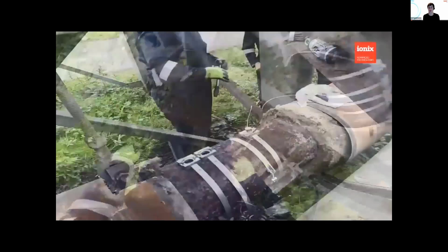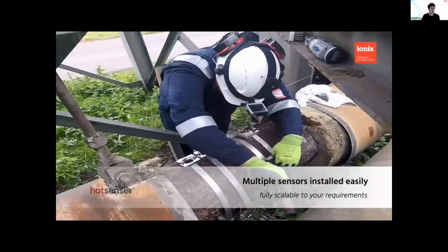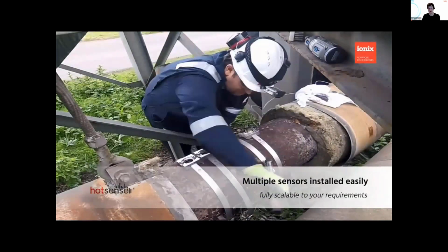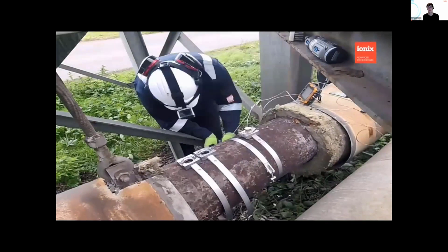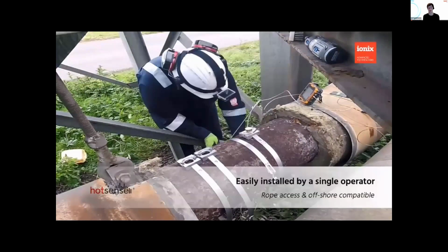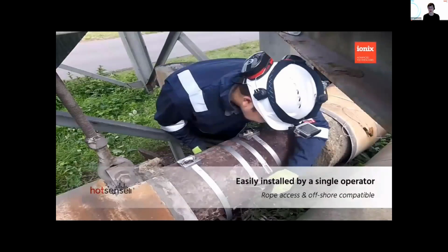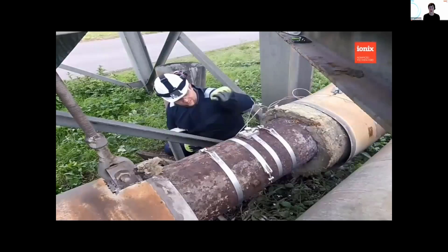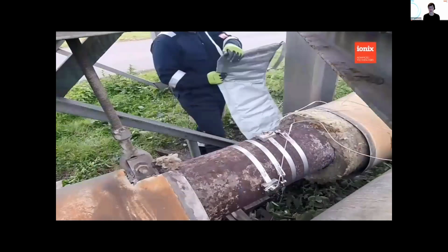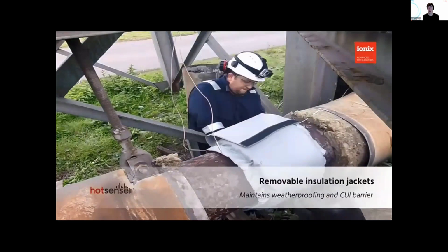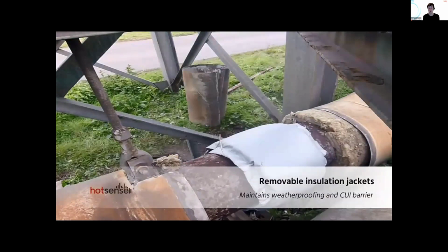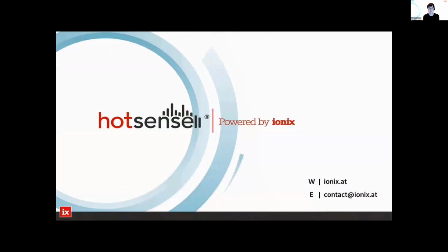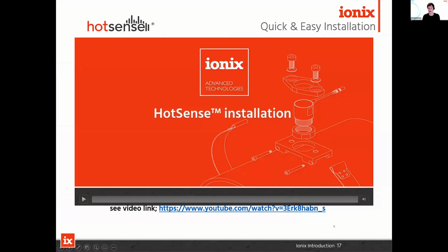It's one probe per strap, but multiple probes can be installed and pushed up next to each other if you want to monitor cardinal points. We do one probe per strap, because this gives really the highest level of security and robustness of the installation. These are often installed in difficult to access locations, and you don't want the sensor coming loose during operation. So going for a single probe per strap is the solution for that. And they're low profile, so you can install insulation over the top with the cables exiting just at joins. In that example, the customer was using temporary insulation over the top because they wanted to re-access that area later. It's another reason they went for the strap probe, so that they could easily remove them.